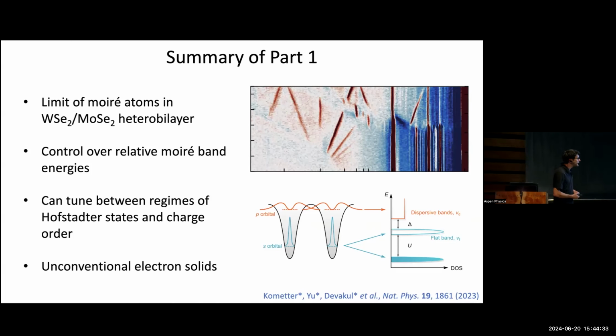Again, let me briefly summarize, and I'll pause for questions if there are any. So we looked at this tungsten diselenide and molybdenum diselenide heterobilayer, and understood it in the limit of Moiré atoms. That is, each Moiré site itself can be thought of as hosting some quantum well, which is like an atom, and you can tune depending on which type of band you're occupying. You can change the relative energies and therefore change preferred ground states. And actually, there are really interesting regimes of charge-ordered states that we still don't have a full understanding of what exactly is going on. So let me pause there if there are any questions before I go on to the next part.